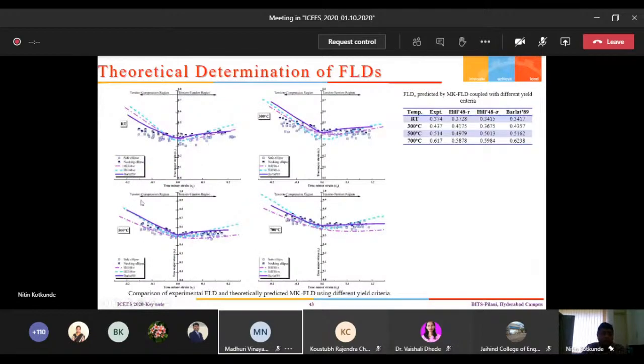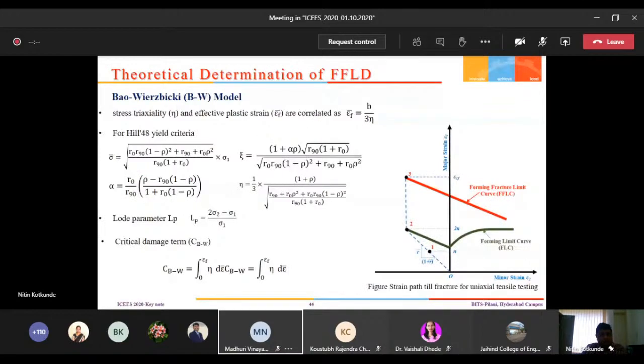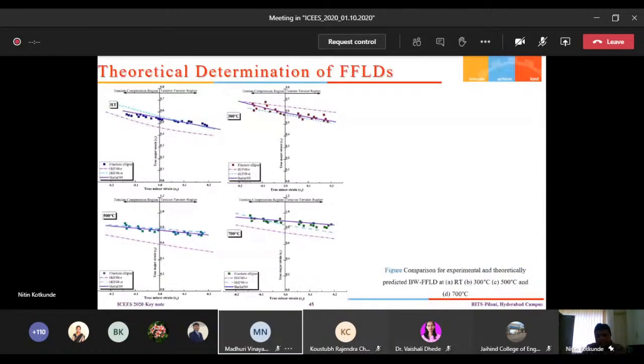Then we have used the BW model to determine the FFLD, fracture based FLD, because the MK model will not be suitable to properly determine the fracture forming limit diagram. So we need to calculate the stress triaxiality and effective plastic strain equation. So we use this equation to calculate the effective plastic strain. Stress triaxiality eta can be calculated based on the actual failure strain in the material. So here we can see that we have used the different fracture models, and we realize that the BW model suits very well. So this is overall the glimpse of our work.